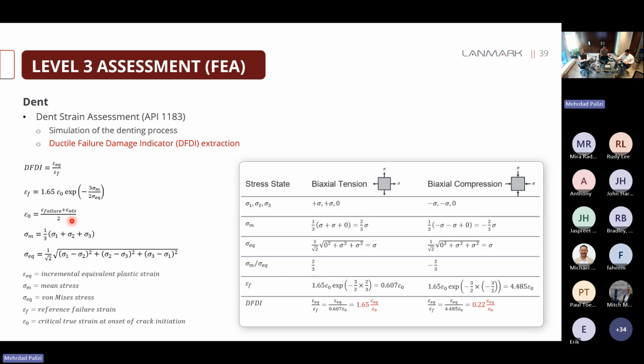At the same time, we can also use this relation to figure it out if we have the material information. This true strain is associated with the ultimate stress. This is going to be the last value for the true strain in the uniaxial material test. So if we take the average of these two values, this is going to give us epsilon 0. So what is happening in this relation here? Actually, I have two examples, one biaxial tension case and one compression case. If we go through the calculations, we can see that for the fracture strain, we are getting much more capacity in the case of the compression, and therefore the amount of damage is much less.